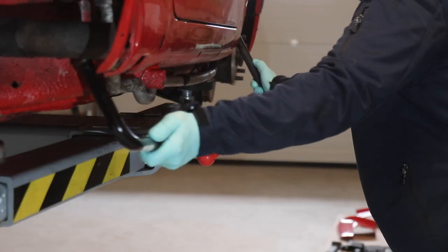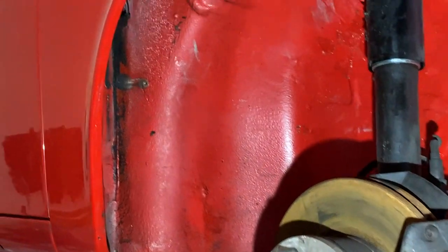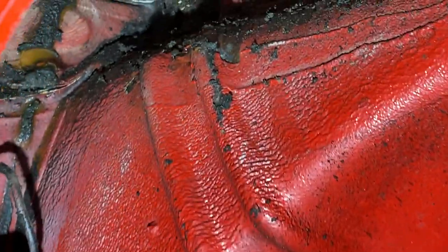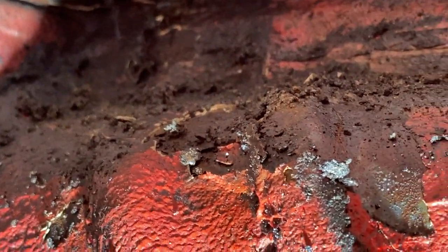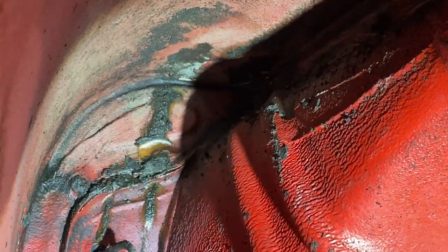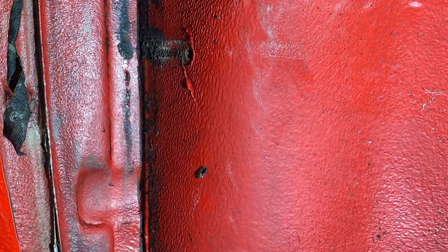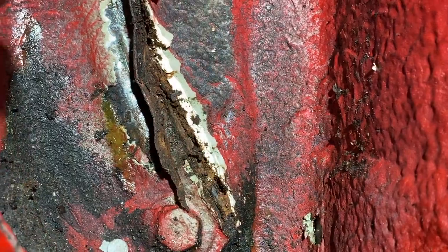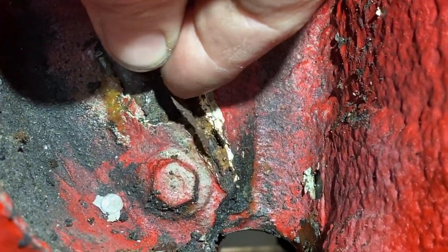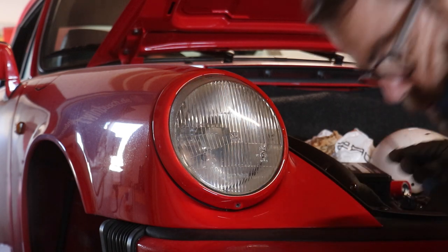In the late years of Porsche's G models, almost all the panels had been zinc coated. I can remember well the fully galvanized 911 body that they had put into the open in front of the Weissach canteen under a tall tree to demonstrate the persistence of this technology to anyone who visited Porsche. They also invested great efforts to line the wheel wells with stone guard, but you see, all these measures have a postponing effect on corrosion, but they can never avoid it completely. To me it became clear at this point that I will have to remove the fender and get to the bottom of the matter.